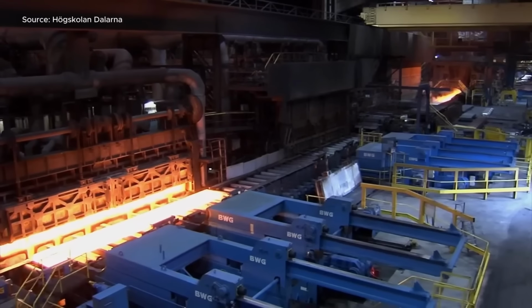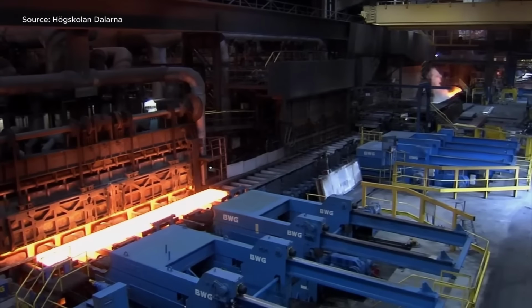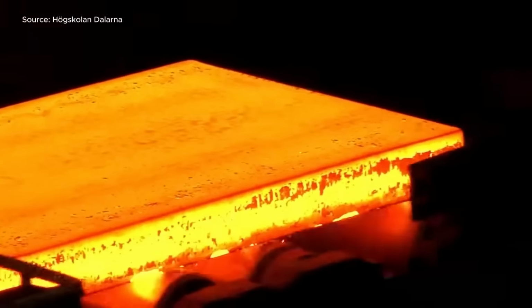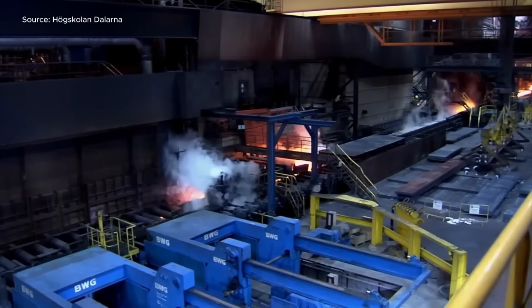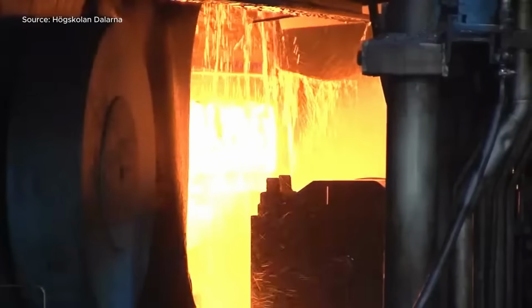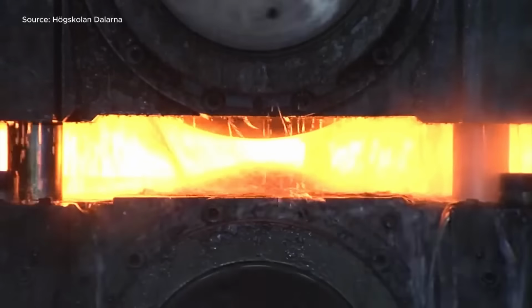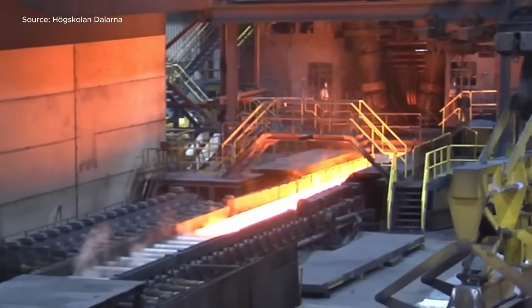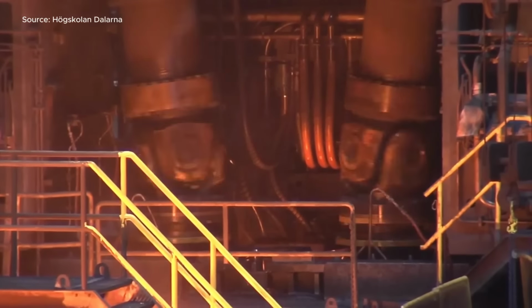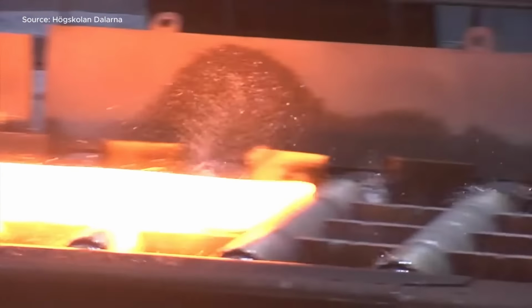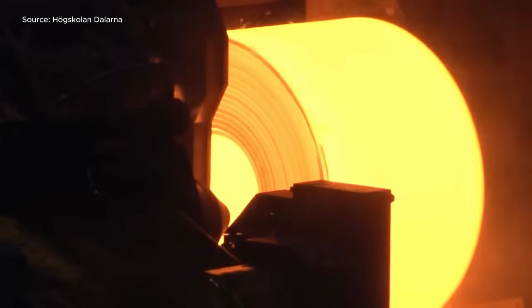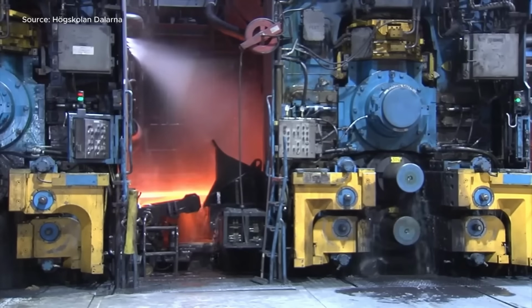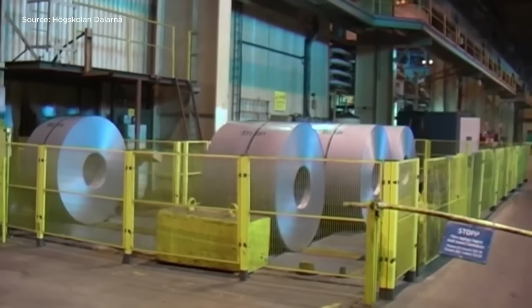The hot rolling mill process begins by heating steel slabs to around 1,200 degrees Celsius in walking beam furnaces. This step ensures optimal metallurgical properties by dissolving carbides and nitrides. The heated slab then undergoes high-pressure descaling to remove surface oxides. In the roughing mill, a powerful 4-high rolling system reduces the slab thickness from 22 centimeters to about 3 centimeters in several passes. The processed slab, now called a transfer bar, is coiled for temperature equalization. It then enters the finishing mill, where it's further reduced to 1.8 to 16 millimeters. Precise control of profile, flatness, and cooling rate ensures the final coil meets strict mechanical and dimensional specifications.